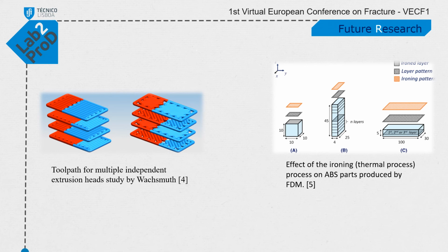Concluding, the results suggest that in material extrusion, seams act in a part by creating a localized fragility, diminishing its properties. The maximum stress achieved in the specimens with seams is coincident with the elastic limit of the material. Accordingly, seams could be considered in the design stage of a product since their location and placement can act as a mechanical fuse. The results lay ground for further studies on the subject, which can be focused on seam properties,